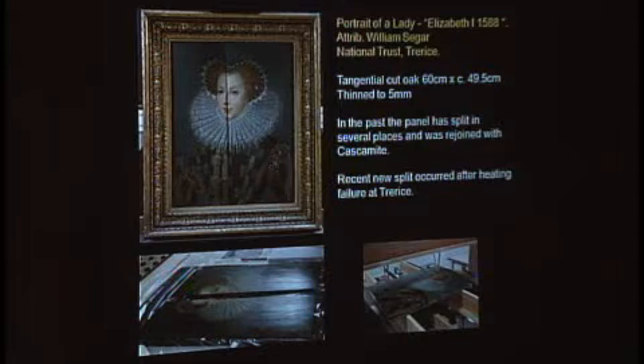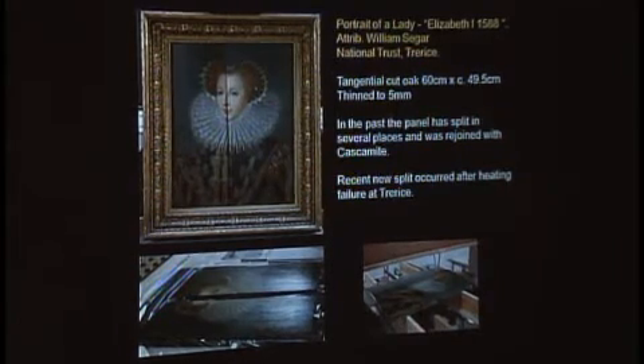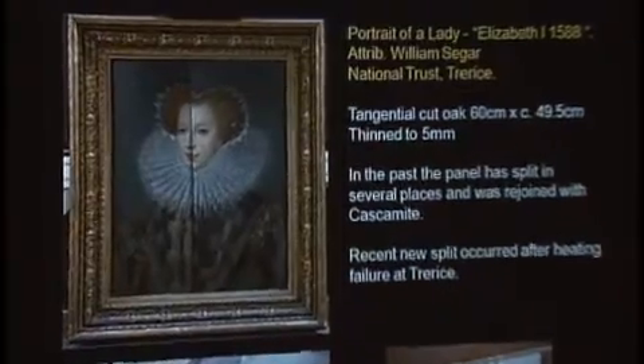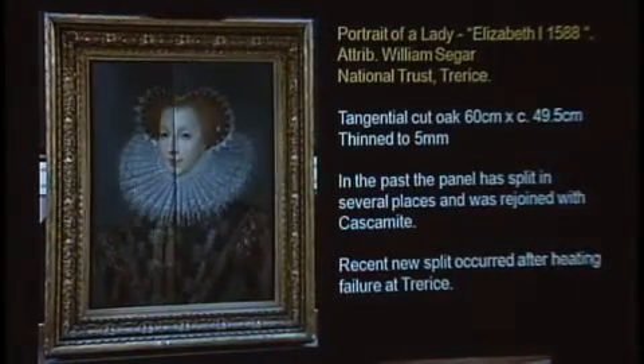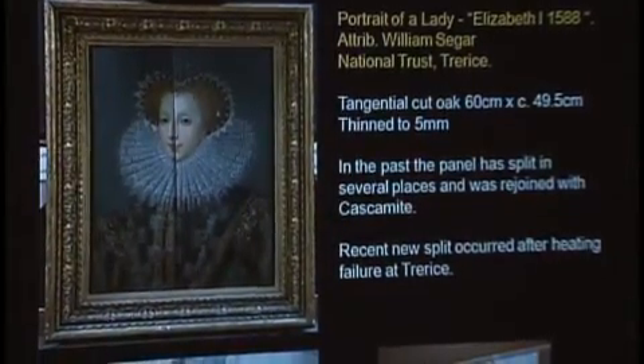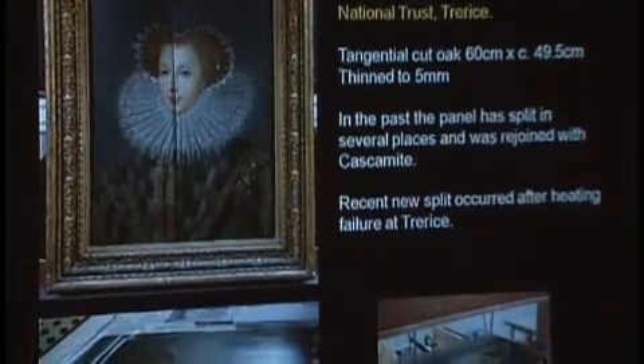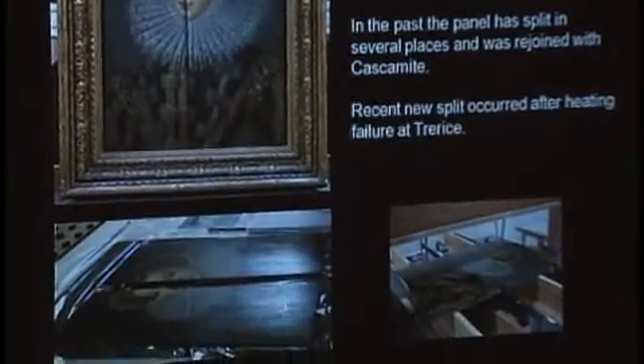Another case for us more recently is this panel from a National Trust property in Cornwall, attributed to William Segar, thought to be from approximately 1600. Again, a tangentially cut oak panel that had been thinned to 5 millimetres thickness. In the past, it had had splits repaired. You can actually see in this diagram at the bottom here the original splits that have been repaired with a phenolic adhesive called Cascamite in the UK, or now called Extramite.